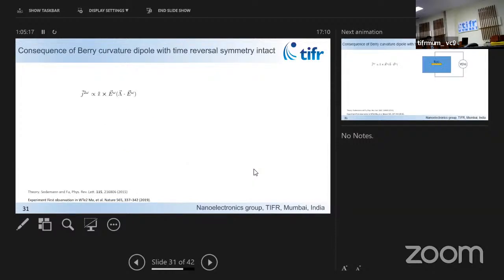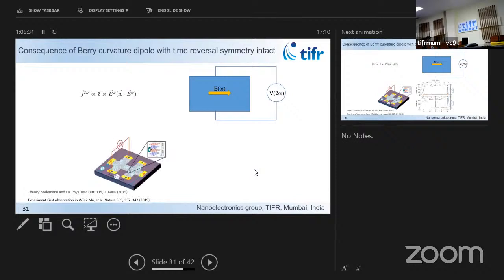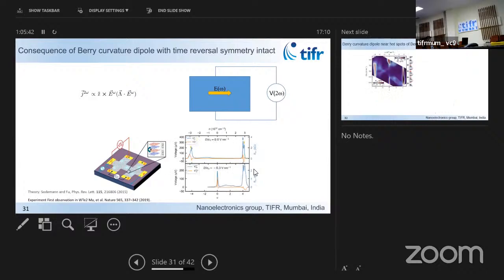So the moment you have a non-zero Berry curvature dipole, you get interesting physics: if you send a current in a device like this at a frequency omega, because of the presence of this Berry curvature dipole, you get a voltage in this direction at frequency 2 omega. It's a kind of nonlinear effect, called the nonlinear Hall effect, and that reflects this Berry curvature dipole. And what we do is, in a sense, measure the Berry curvature dipole through this nonlinear Hall effect. So this quantity in orange is the V2 omega xy. xy reflects the Hall signal.